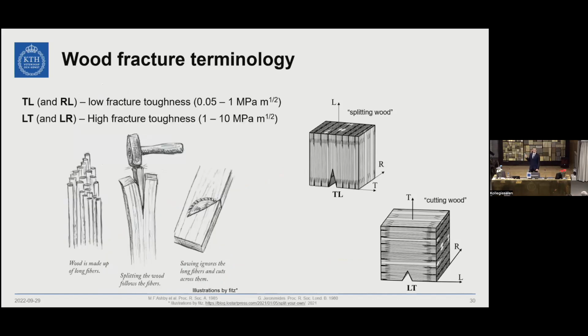If we compare these two different types of fracture behavior, we can see that when splitting the fiber, with the crack growing along the fiber direction, the fracture toughness is quite low compared to the other direction, where you have to propagate through the fibers. And this is one of the reasons why splitting wood is so much easier than cutting through the fibers. We usually use machines to get this clean cut.